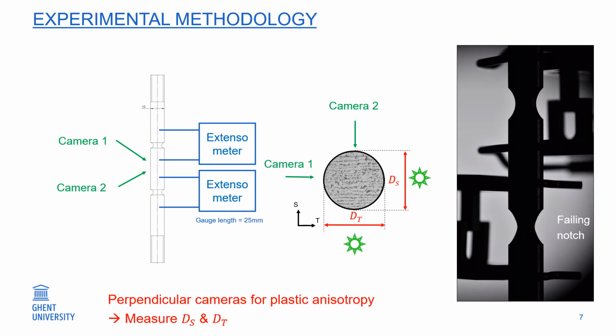We want to use load deformation curves to calibrate the damage model. For this reason, an extensometer was placed around each notch for obtaining the axial elongation. Two regular cameras were perpendicularly positioned for extracting the diameter reduction, in the transverse T and the thickness S direction. The reason that two cameras were installed is that anisotropy might be expected for pipeline steel. Behind each camera, a light was placed to obtain a high contrast picture, such as this one on the right.